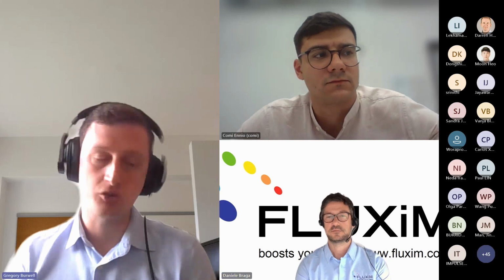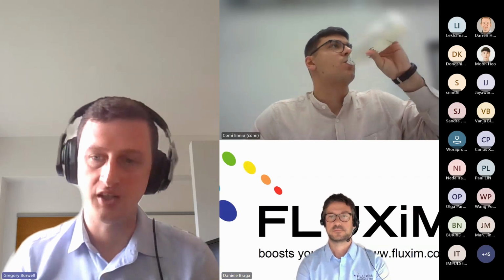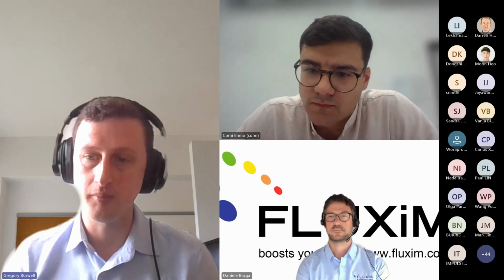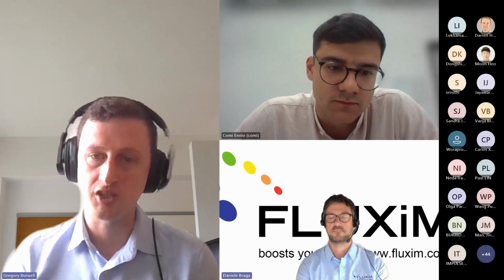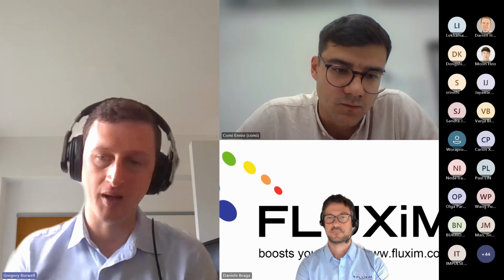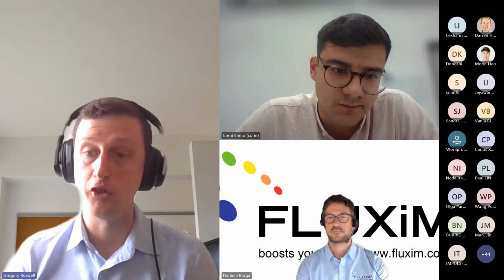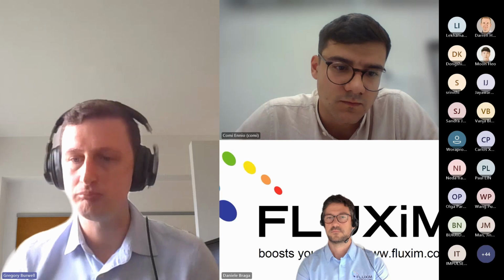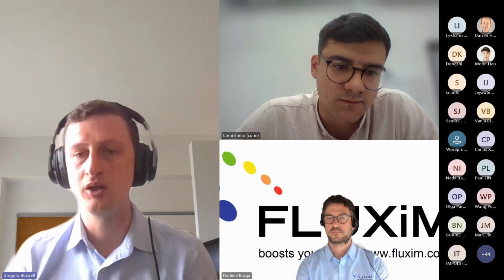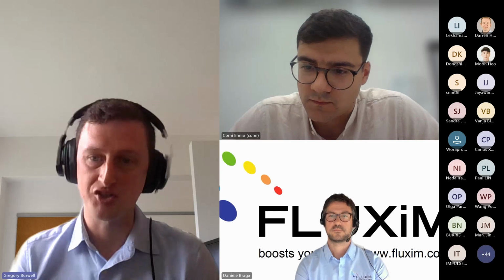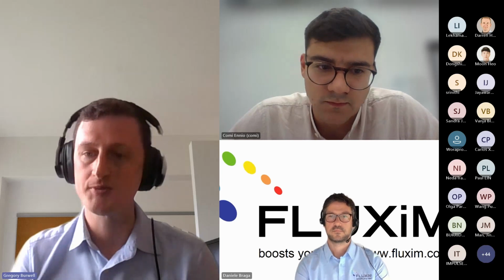We have tried, yeah. So we have done some comparisons. We find, due to the geometric packing, that the honeycomb is usually the most efficient to use. That's why we tend to stick with that now, and that's what we fabricate in real life. It's a nice thing about using a lithographic-based technique that we can have any shape we want, basically. So we can do more complicated structures like honeycomb as opposed to just doing rectangular grids.